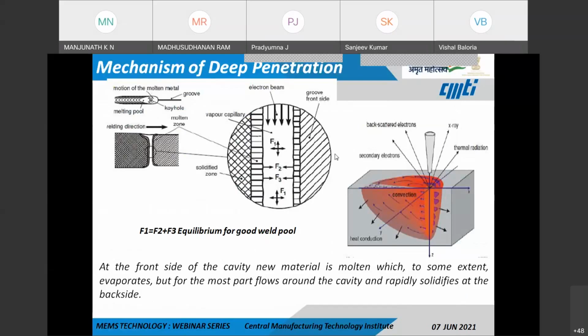So here with this graph, we can see that once the electron beam is coming, F1 is the force of the vapor pressure. And then F2 is the force resulting from the surface tension of this molten weld pool. And then F3 is the hydrostatic pressure which is acting within the system. So for equilibrium, the force F1 has to be equal to F2 plus F3.